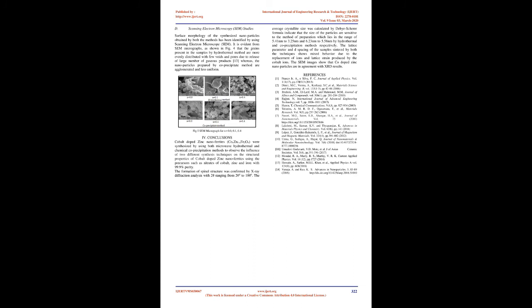4. Conclusions. Cobalt-doped zinc nanoferrites, CoxZn1-xFe2O4, were synthesized by using both microwave hydrothermal and chemical co-precipitation methods to observe the influence of two different synthesis techniques on the structural properties of cobalt-doped zinc nanoferrites, using precursors such as nitrates of cobalt, zinc, and iron with 99.9% purity. The formation of spinel structure was confirmed by X-ray diffraction analysis with 2θ ranging from 20° to 100°.